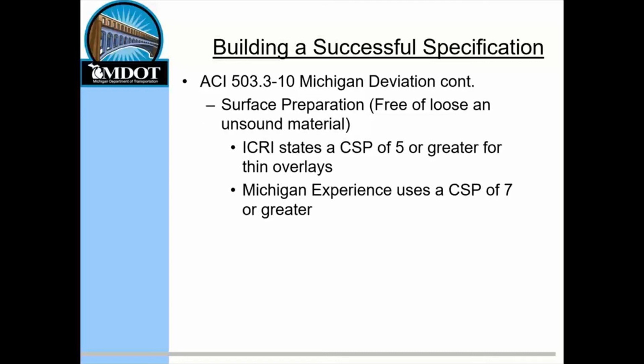Another deviation: the ACI spec only indicates that the surface to receive epoxies is to be free of loose and unsound materials and contamination that will affect the cure or adhesion. We look toward ICRI. The ICRI states a CSP of 5 or greater for thin overlays. So in Michigan's experience, to get the 20 years and guarantee that we're getting adhesion, our spec calls for a CSP of 7 or greater. Really, that's to help out our inspectors. If the contractor is only shooting for a CSP of 5, there could be areas less than a 5. But if they're shooting for a CSP of 7, you're almost guaranteed to not have any areas on the deck less than a CSP of 5.